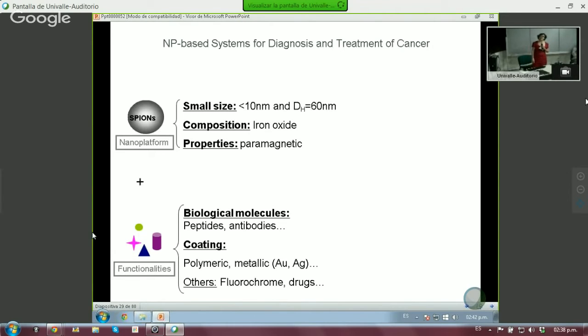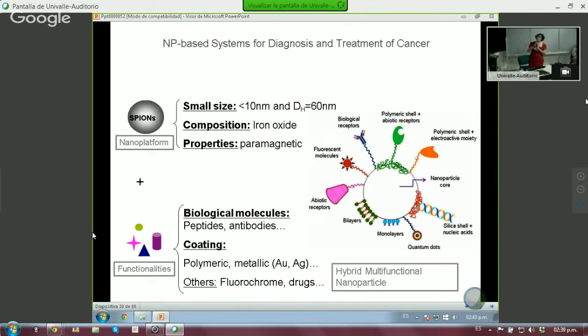Okay, and so we stayed at small size. We stayed less than 10 nanometer with a hydrodynamic diameter of about 60 nanometer, and we aimed at the paramagnetic. And then these are the biological molecules that we considered. We did the coating in two ways. We did some with polymers, but I will not talk to you about that. We also used metallic coatings like nano gold and nano silver, because these are not toxic and they have interesting properties. And the other thing we used, of course, was fluorochrome and the drugs. So essentially, this is a nice picture because it shows you everything which went around these nanoparticle cores. And it's amazing how nowadays one can achieve such a construction experimentally in the lab.